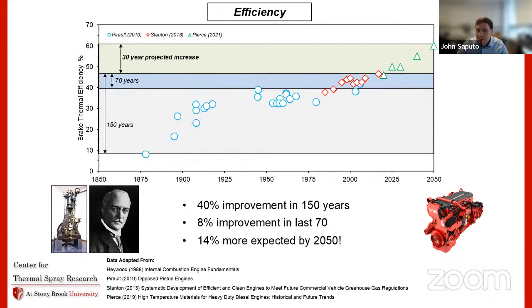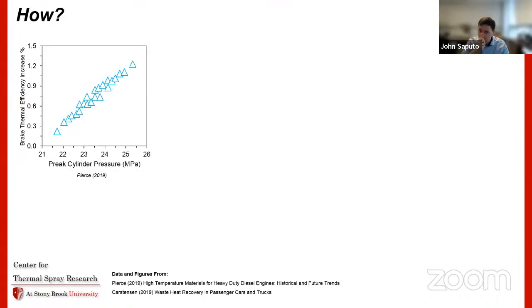But you can kind of look to how people in this field project that this will actually work. There's a couple of things that people look at. The first is looking at efficiency versus peak cylinder pressure. Some of the ideas that people have in this field is that you can just increase the working pressure that these things work at. You increase the amount of work that comes out of an engine, and the efficiency of it will go up. So increasing the pressure has a direct correlation to increases in efficiency, and is projected to have about 1 to 3% impact on that total 14% that I mentioned.